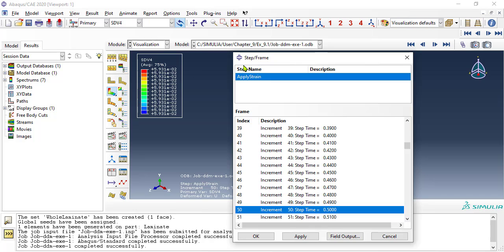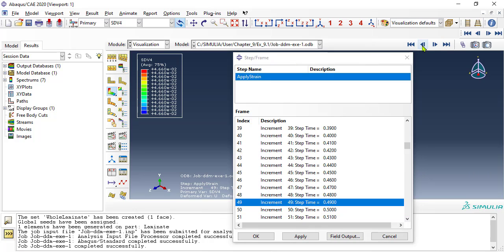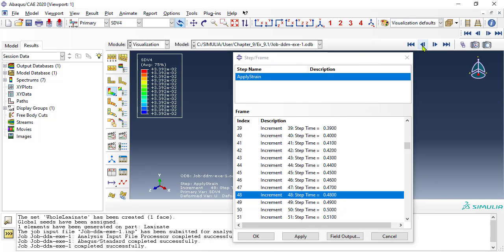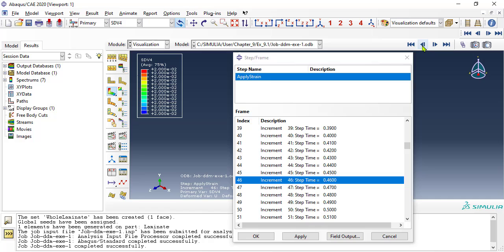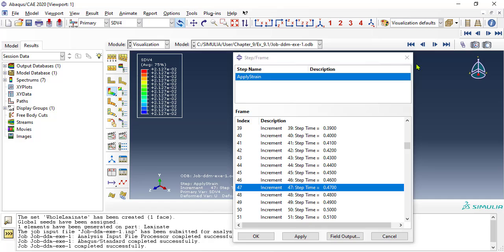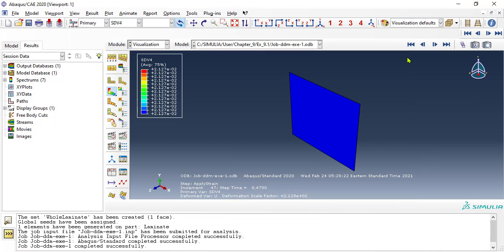By playing with this table, you can pinpoint the frame, time, and strain at which crack initiation takes place, when the crack density jumps from 0.02 to a higher value. You are seeing the center lamina. Other laminas crack at different strain or do not crack at all.